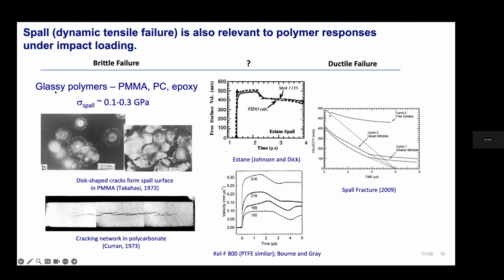So we know there's historical literature looking at glassy polymers where samples were recovered after spalling them using shock and release. What they noted was that for glassy amorphous polymers such as PMMA, polycarbonate, and epoxy, the spall strengths are quite low, so it's pretty easy to observe, as far as the shock condition, damage in the material. And you can see, this is work on PMMA and also polycarbonate. They have very brittle crack-like behavior.